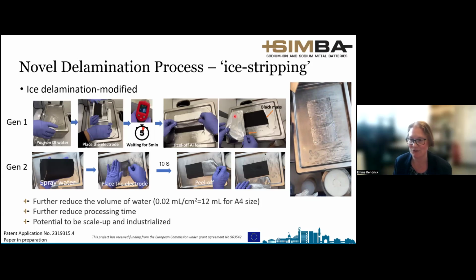It's placed onto a cold plate or in this case, an ice cream maker, and the electrode sticks to the surface, and we can simply peel off the electrodes, leaving very little active material left behind on it, in a quite pure aluminium foil. And in this process, we use very little water indeed.